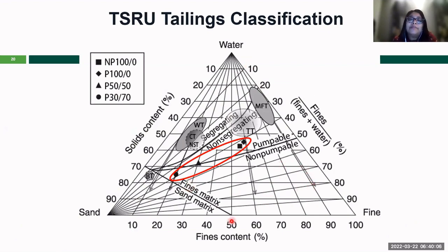This ternary diagram describes the behavior for different types of tailings. These points here are our data for the 4 different kinds of materials that we tested. All samples were classified as non-segregating. As you can see, they fall below this line. Above that line are the segregating materials, and below this line are non-segregating. So all these materials are non-segregating. And if you look at the data, other than the 30%, all of them are pumpable. So we can characterize them as non-segregating pumpable material, except for this 30% data point, which is outside of the